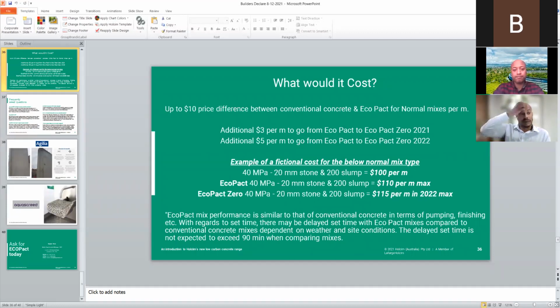As we push EcoPact concrete, and with the lovely weather that we have in Melbourne, which is typically fluctuating up and down and more towards the colder side, I do want you guys to be aware that GP Portland cement is typically the one that gives us most of the robust properties of concrete, whether that be strength, whether that be set time, and so forth. So as we use more and more supplementary cementitious materials such as slag, silica fume, or fly ash, we do start to compromise on some of the set times.